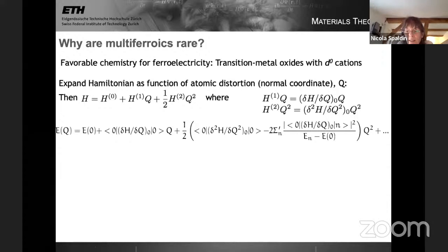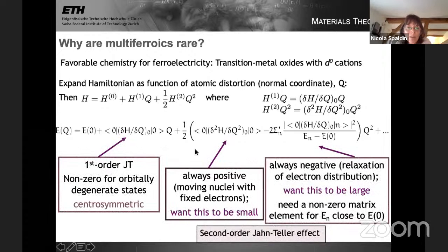Let me show you what these mean. So the first order term again describes the regular first order Jahn-Teller effect. It's non-zero for orbitally degenerate states, and it's a centrosymmetric distortion. This second pair of terms is sometimes called the second order Jahn-Teller effect. And if this is energy lowering, then it's energetically favorable for the system to become ferroelectric.